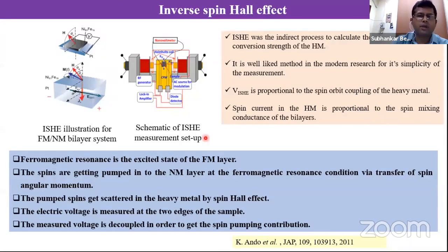The same setup you can basically use for the inverse spin Hall effect. You put the sample, you do the same experiment. Now the small modification you make is you put contacts at the edges, and you connect to a nanovolt meter, and you measure this voltage which is arising because of this spin current. So basically the spin to charge conversion.